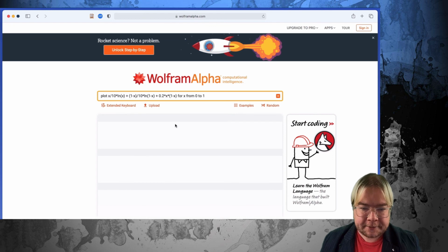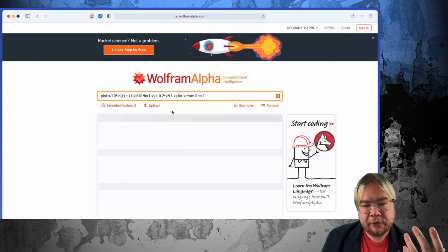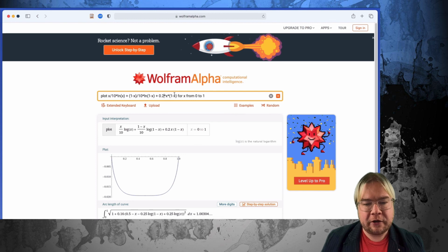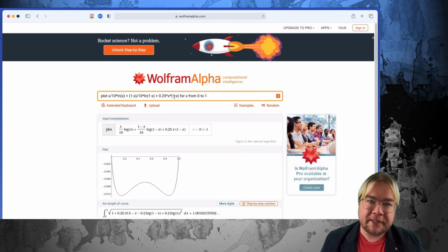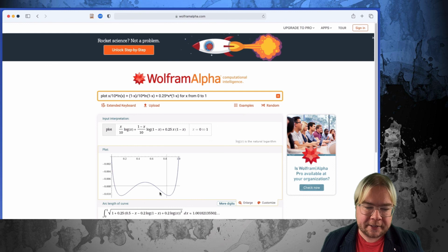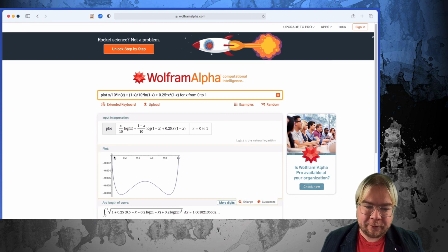So let me go back to this case. Instead of increasing the degree of polymerization, watch what happens if I start increasing the value of the chi parameter from 0.2 to 0.25 maybe. I'm just kind of picking values. You see the shape of the curve that we have here. We get this kind of W-shaped curve where we have two minima, one maximum across the volume fraction range. So this shape of curve is going to have serious implications on whether or not polymers mix together. And I will say that for this system, sometimes they will mix together and sometimes they won't.